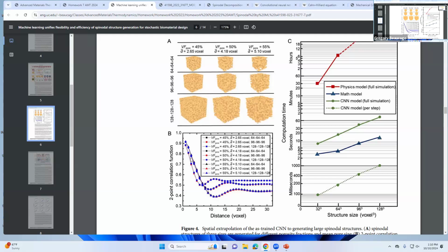So you expect if the sizes of the things are smaller, which they are in this case, because the peak's to the left, then you get a larger number for the surface to volume ratio. Right, smaller has a larger surface to volume. And it's steeper, so that's good. So that one's okay. Then as you get to higher constant and larger phases, then you expect the slope to be shallower, and it is, but it isn't changing for the last two. It's the same surface to volume, whether you have 50% or 45%.